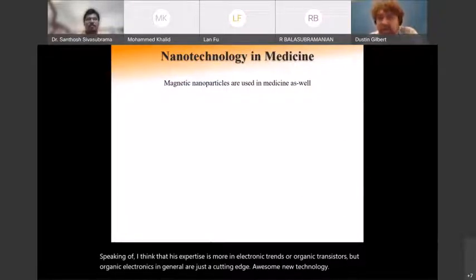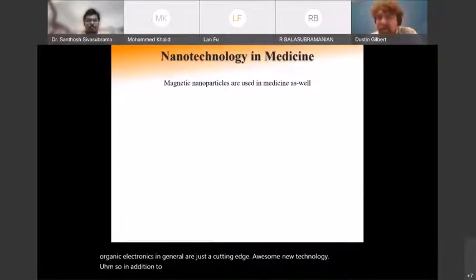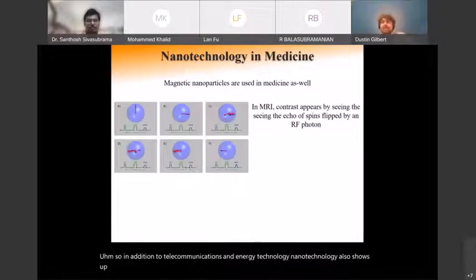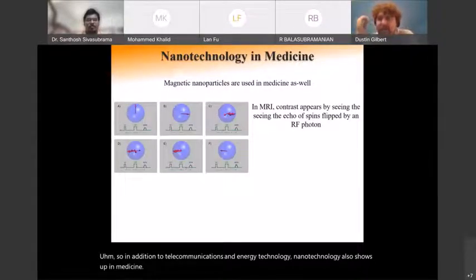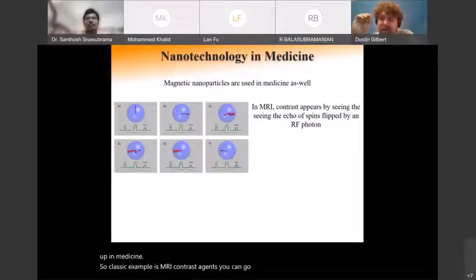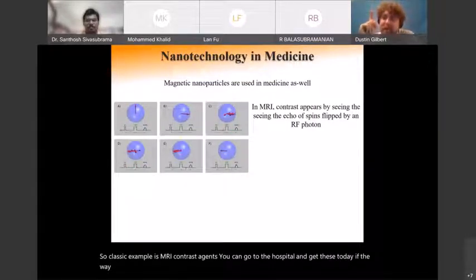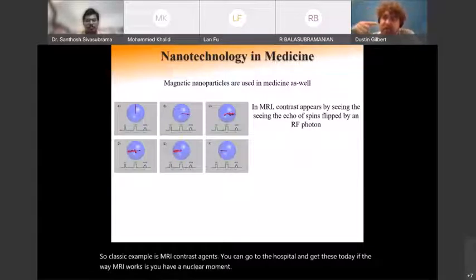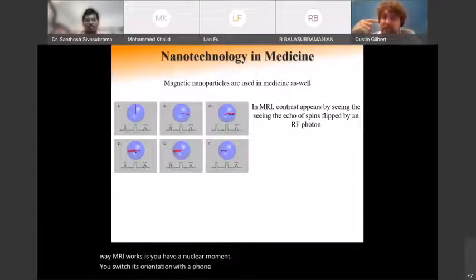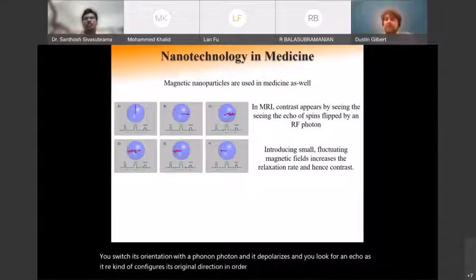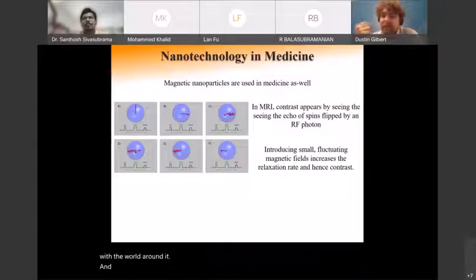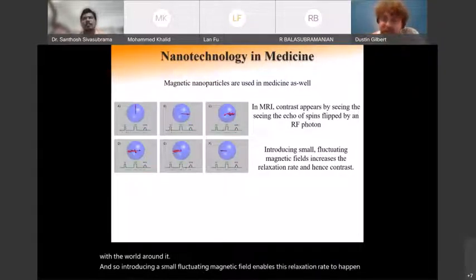So in addition to telecommunications and energy technology, nanotechnology also shows up in medicine. So classic example is these MRI contrast agents. You can go to the hospital and get these today. The way MRI works is you have a nuclear moment. You switch its orientation with a photon, and it depolarizes, and you look for an echo as it kind of configures it in its original direction. In order to do this, it must exchange angular momentum with the world around it. And so introducing a small fluctuating magnetic field enables this relaxation rate to happen faster and hence increase the contrast.